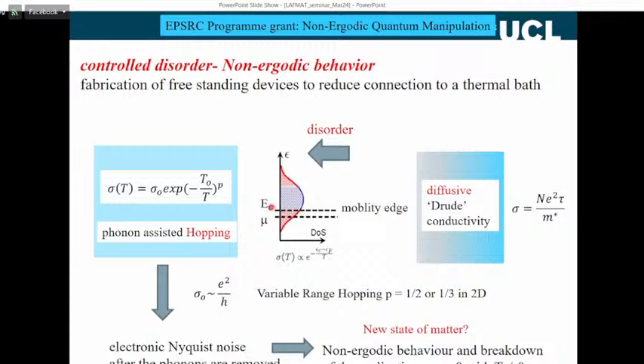When the chemical potential or the Fermi energy is below the mobility edge, we have to thermally excite carriers up to the mobility edge to measure the conductivity. So we have a kind of exponential dependence of conductivity. This was covered last week in the talk by Professor Granato. What we should see in these systems is that the system goes over to hopping. So we have a temperature-dependent conductivity with a characteristic energy of the mobility gap, T0 as a temperature, and there's some power law that comes in.